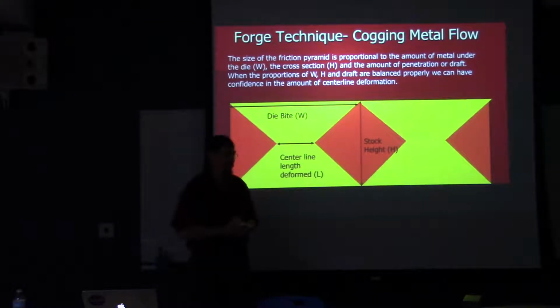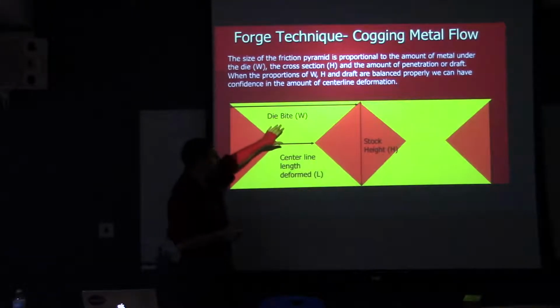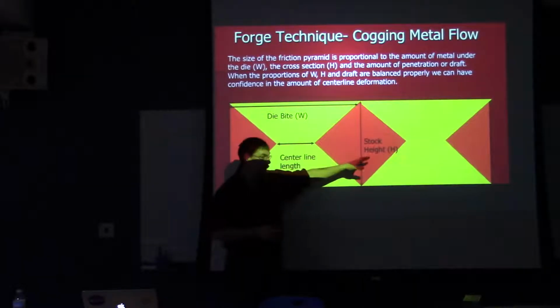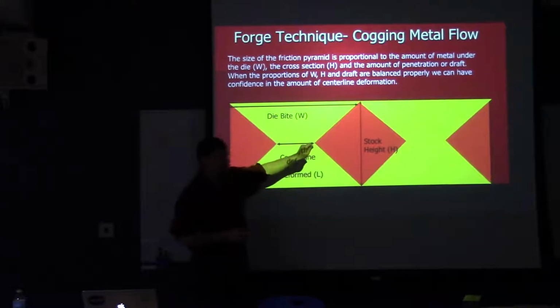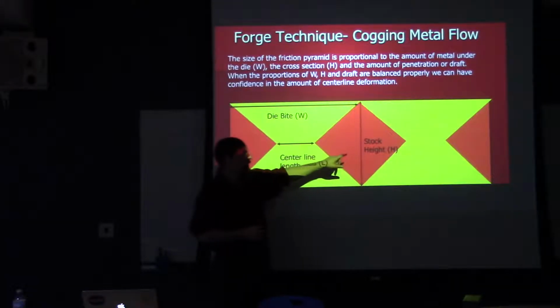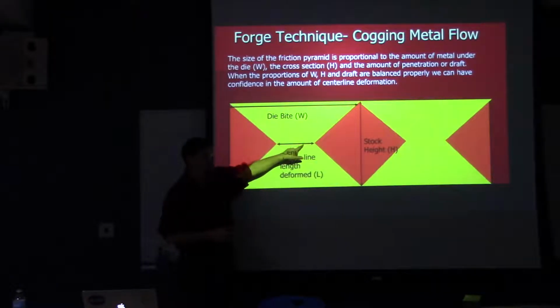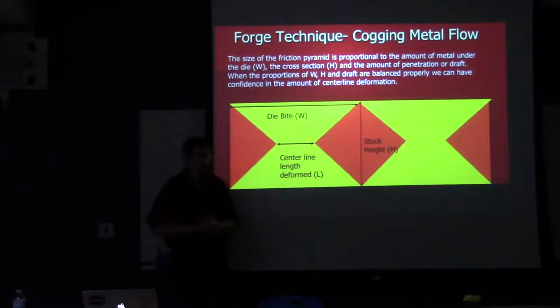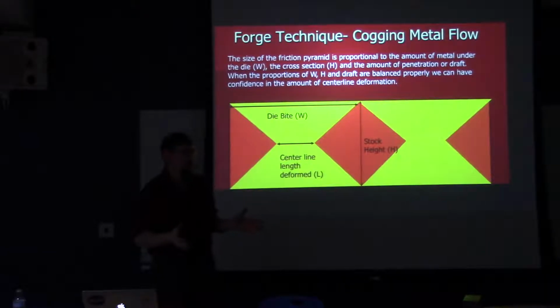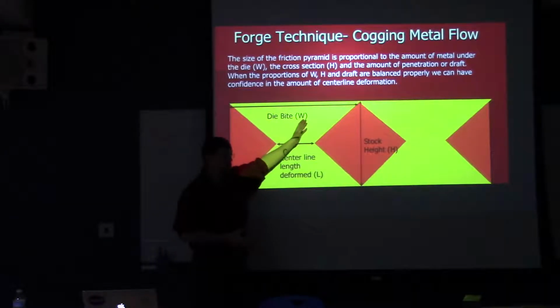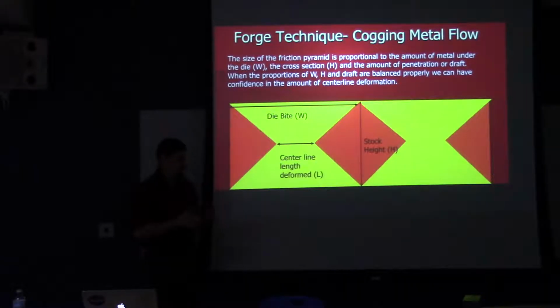What are these equations again? Okay, so the equation is, if W equals 1/2 of H and the draft is 20% of H, then our dimension L here will be 1/3 of W. So if I have a 30-inch wide die and I take a full die bite, all 30 inches, and I have a 10-inch cross section and I reduce that from 10 to 8 with a 30-inch bite, I'll have 10 inches deformed along the center line. Right? That's what that means.